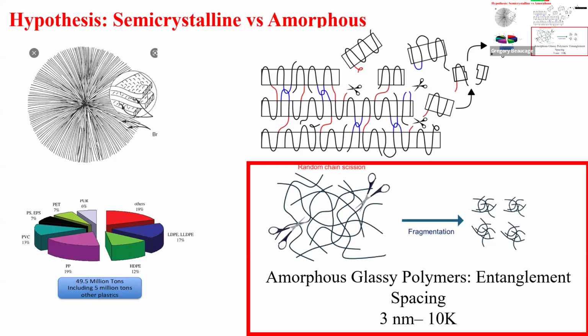Contrast that with the semicrystalline polymer state. You've taught them semicrystalline polymers, right? Yes. Okay. So you have alternating crystal and amorphous regions, right? So imagine I put oxygen in there. The oxygen is only going to go into the amorphous phase. It's not going to go into the crystal phase. So the bonds are only going to break in the amorphous phase, okay?